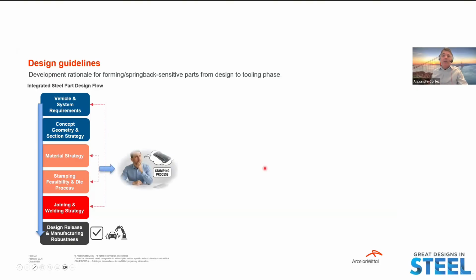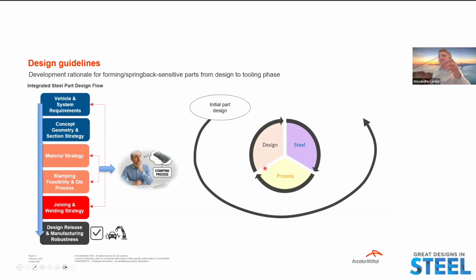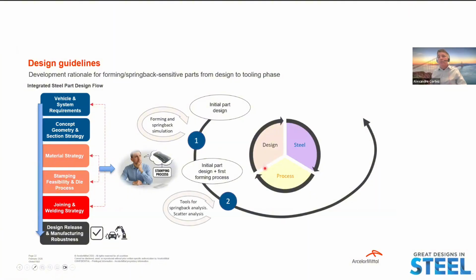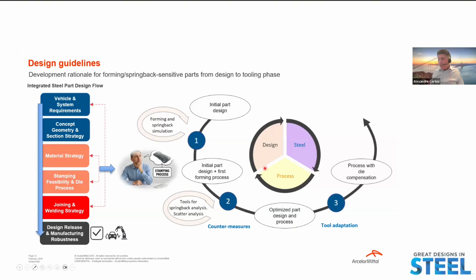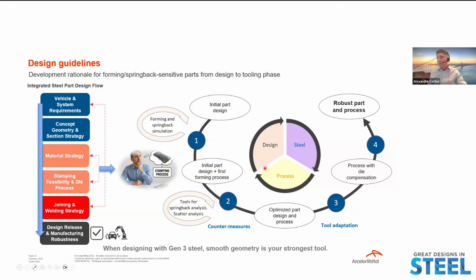I would like to highlight these two steps here: when we start to design, we must add the stamping process in our concept. We have this kind of methodology in ArcelorMittal, developed by ArcelorMittal R&D. From the initial part design, we do an evaluation to check the forming and the spring back with virtual simulations. Then we have the initial part design and the first forming process defined. Then we develop tools for spring back analysis and scatter analysis, and we implement the countermeasures. Then we have an optimized part design and process, then tooling adaptation, and then die compensation if needed. And in the end, we have a robust part and process.